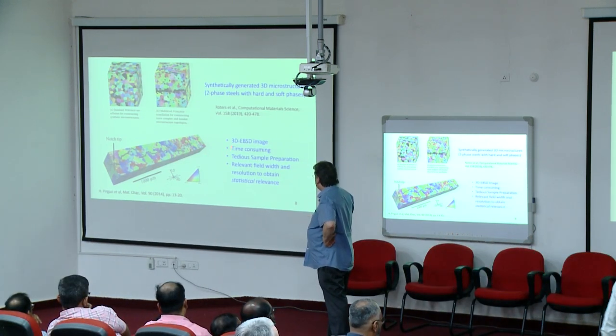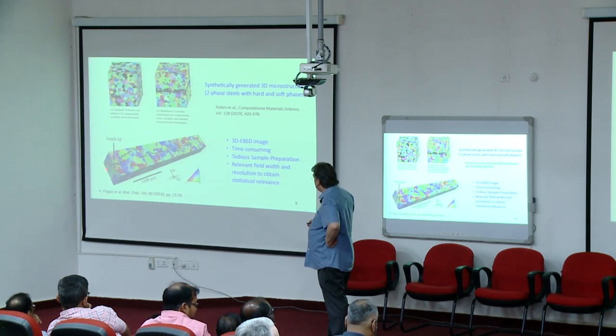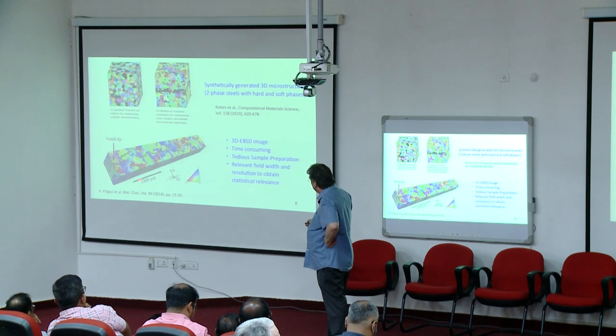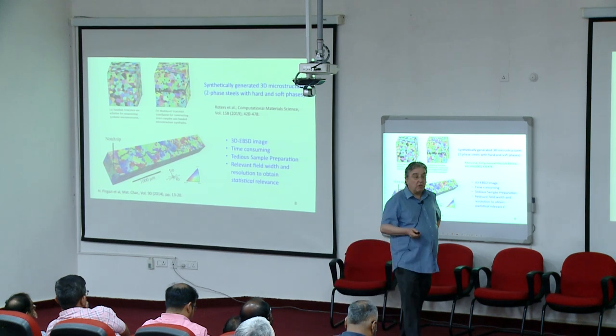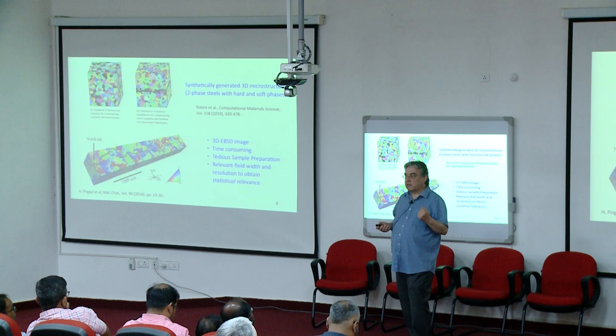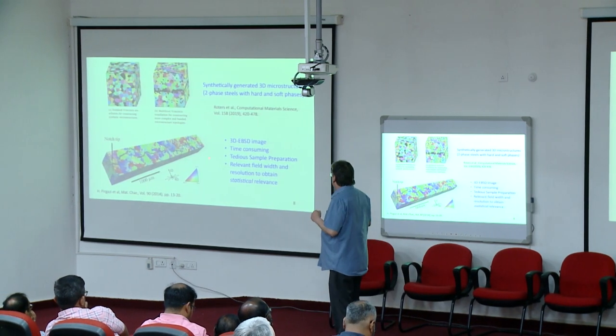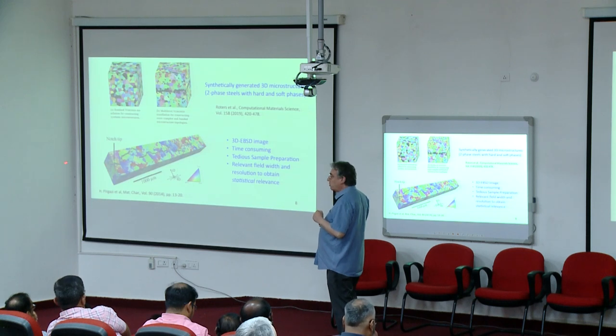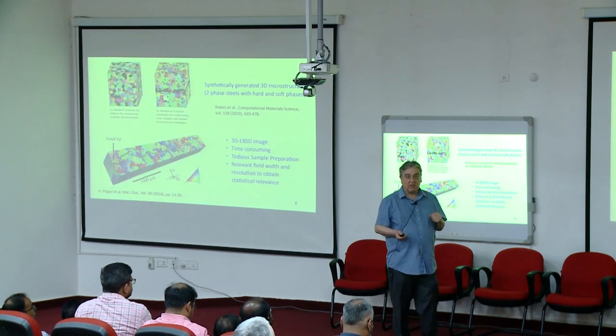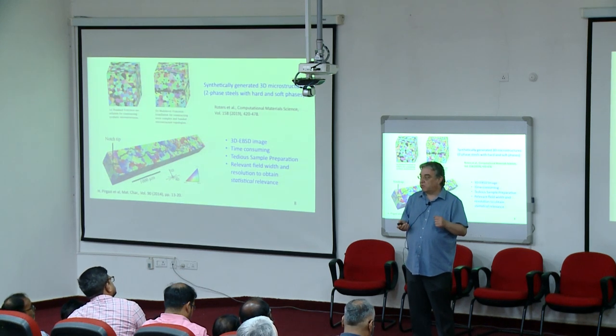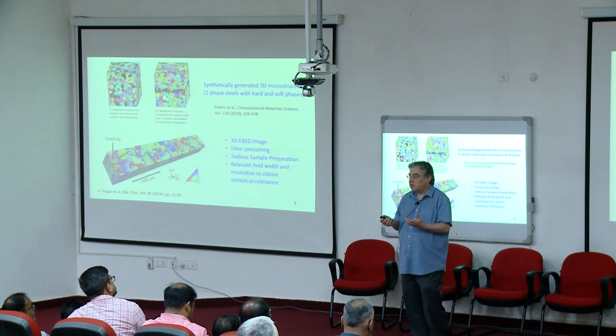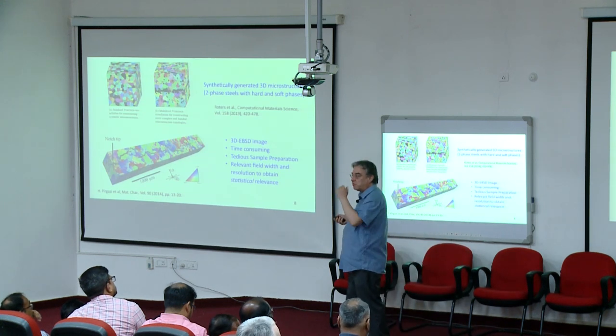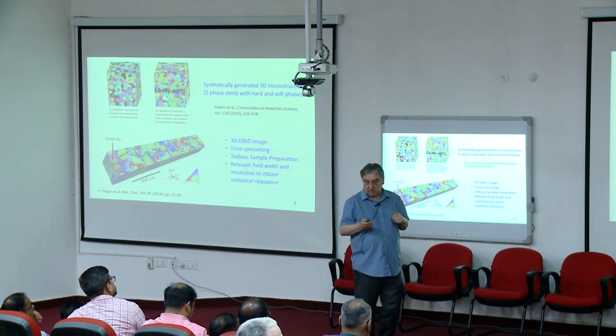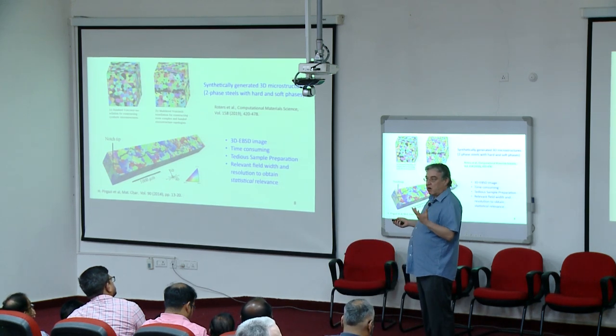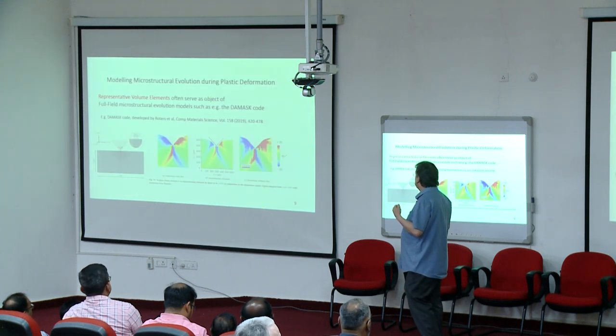This was a 3D EBSD image of a cast iron that we have made in Ghent by ourselves, and you can see how it's a very wide field. This is 1 millimeter. And here you can see a crack, and we visualize this crack. This was a thermomechanical fatigue crack. Of course, this is a lot of work. Making such one image for one material is easily 3 weeks of work of electron microscopy. So it's not very convenient. You're not going to do this for 10 different materials, for example, because otherwise it's too long. So that's why there is a necessity of creating virtual microstructures.